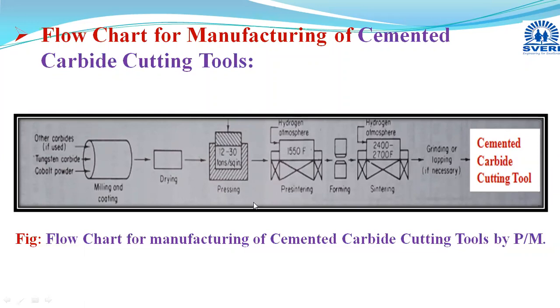Then, after completing this pressing in 3 stages, by filling the die cavity, then sufficient pressing and obtaining the green compact by ejection from that die cavity, that component is subjected to the pre-sintering.